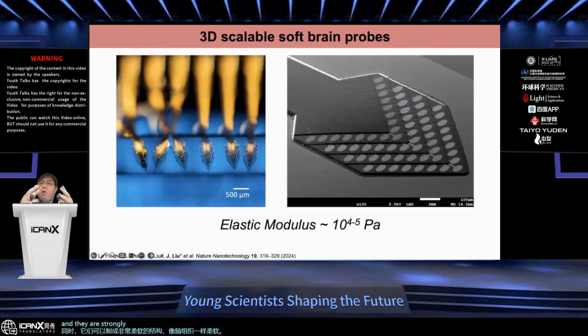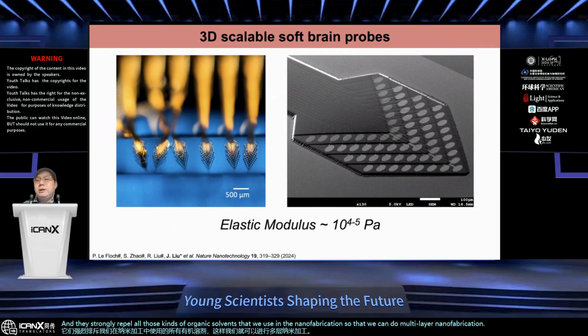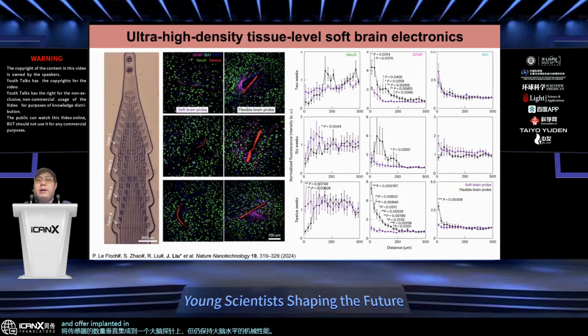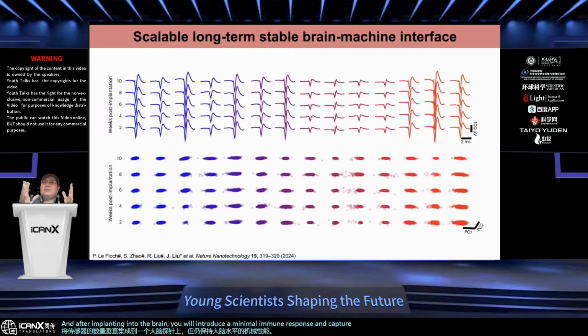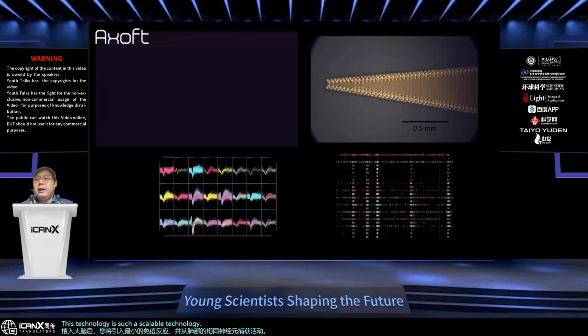And they strongly repel all those organic solvents that are used in the nanofabrication, so that we can do multi-layer nanofabrication, vertically integrate a number of sensors onto one brain probe, but still maintain the brain-level mechanical property. After being implanted into the brain, you will introduce minimal immune response and capture the activity from the same neurons over a long time. This is such a scalable technology.